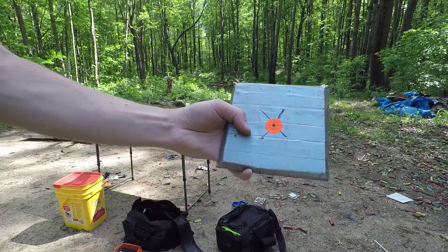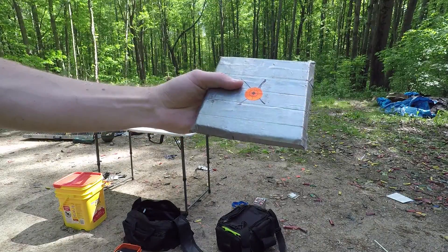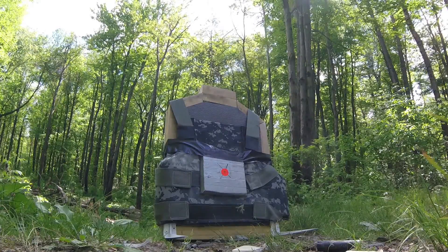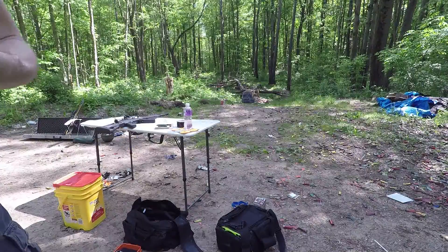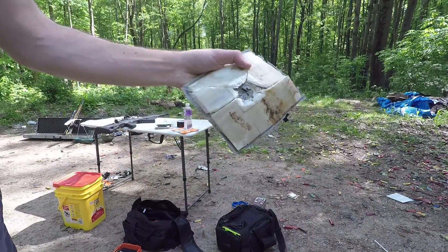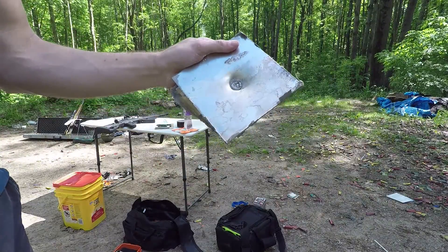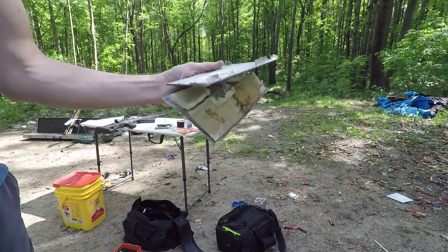This one is 12-gauge mild steel with marble plates on the outside. Same as before — shattered the tiles, didn't penetrate the steel plate. This one almost did, so I think 10-gauge would probably be the lower limit of what you'd want for this type of plate.